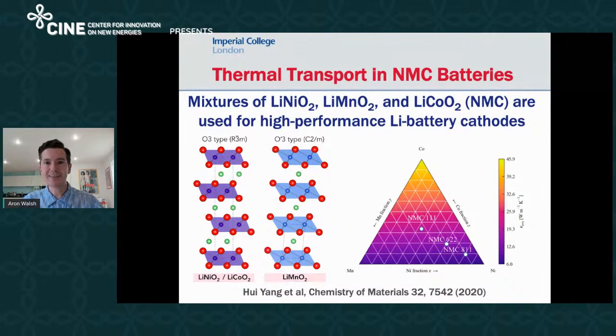So I'll just give two examples of some of the research in my group that's using these more conventional methods. We have a big active project in the UK called the Faraday Institution, related to battery research. And some of our work is understanding thermal processes, which can be related to degradation, but also to some performance issues. Using tools looking at phonon frequencies and phonon lifetimes, we can predict thermal transport across some quite complex solid solutions. So looking at mixtures of lithium, cobalt, manganese, and nickel oxide, and how the vibrations change, but also how the difference in heat retention changes through that phase diagram. Those types of simulations just wouldn't have been possible 10 years ago because of the expense involved in computing these phonon-phonon interactions.